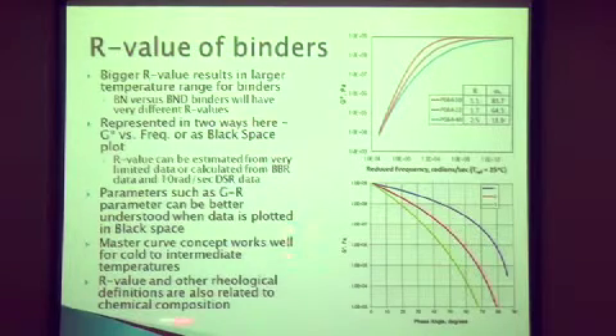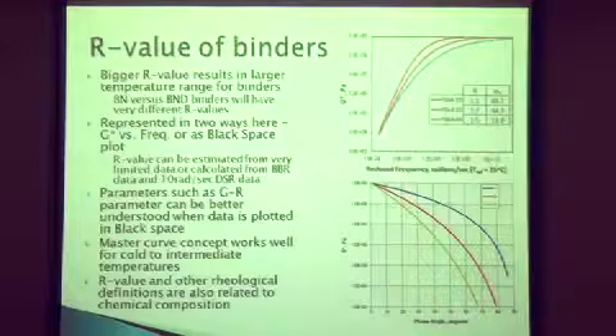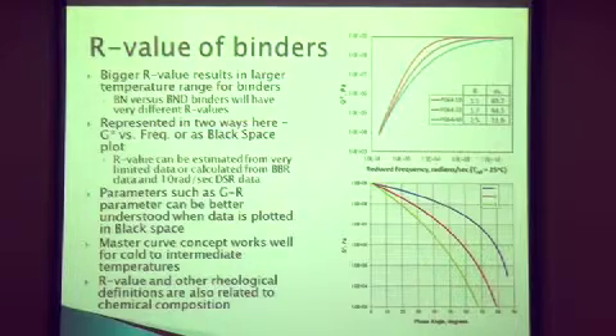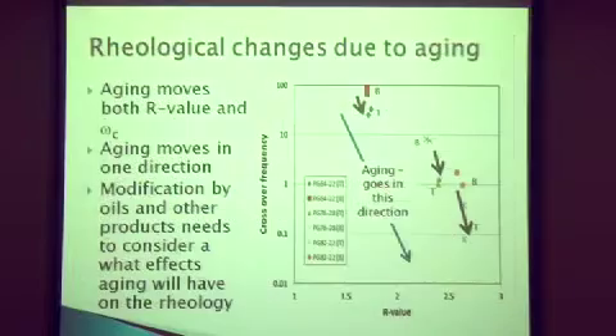The other thing to note is that this rheological index, R value, is also related to the chemical composition. So depending on the refinery you use, the oil wells, the type of oil going into that bitumen will affect performance like this. Also, as that material oxidizes and ages, it will change stuff like this. As you oxidize materials, you make more asphaltene, and some of the resins and saturates, as they oxidize, tend to become more asphaltene parts of the bitumen. This is what we see that occurs when we age. With aging, the R value, the rheological index, increases, and the crossover reduces. So you basically change the shape of the binder's rheological curve.